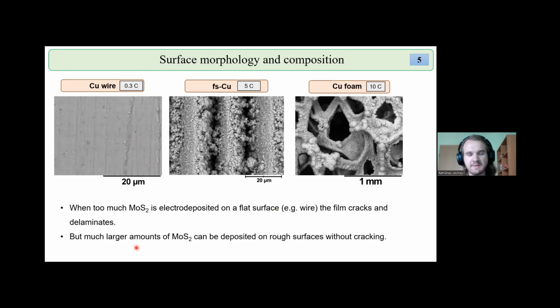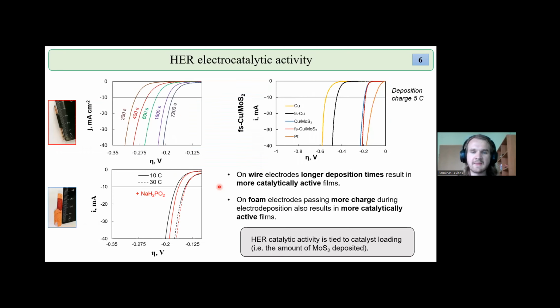Whereas on rougher, more evolved surfaces, larger amounts of molybdenum sulfide can be deposited, and for various reasons, the film is not compact and thin, but perhaps more microstructured, and therefore it adheres better to the substrate, which matters a lot for the stability of the film. So we measure hydrogen evolution reaction electrocatalytic activity by drawing linear sweep voltammetry curves in an acidic medium, 0.5 molar sulfuric acid. Again, the three different substrates are compared here.